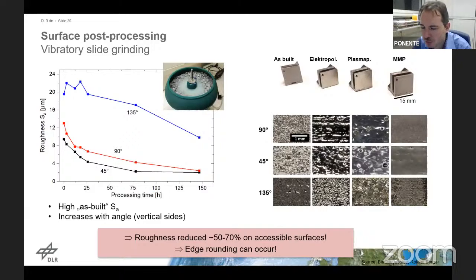If you nowadays walk about over the Formnext conference or big market show in Frankfurt that we have every year on 3D printing, there are more and more companies that provide services in terms of surface post-processing for parts and specimens. On the right-hand side, you see a couple of examples with some light microscopy images of the specimens after machining. And you see that, for instance, plasma polishing or this micro machining process, MMP, leads to much smoother surfaces.